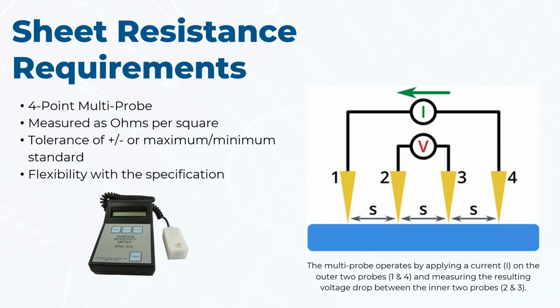Tolerances: if you can't specify a maximum and you can't specify a minimum, one of the things to keep in mind is a plus or minus tolerance. Maybe it has to be 50 ohms per square, but I know my system will operate if it goes up to 75, and I know it'll operate if it goes down to 25. So what we'll say on that specification is sheet resistance requirement is 50 ohms per square plus or minus 25. And that's really an easy way to specify it.